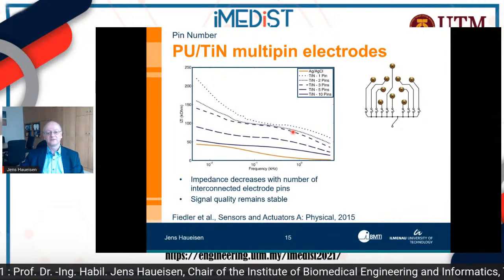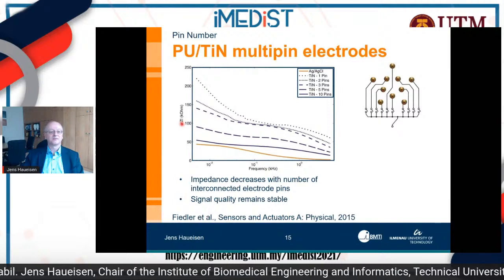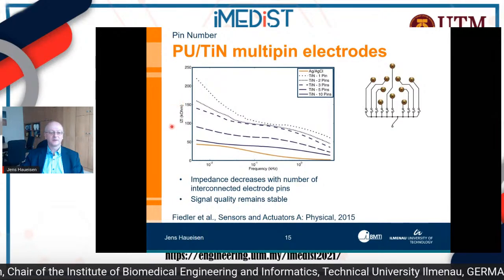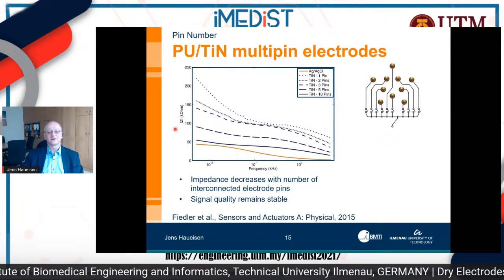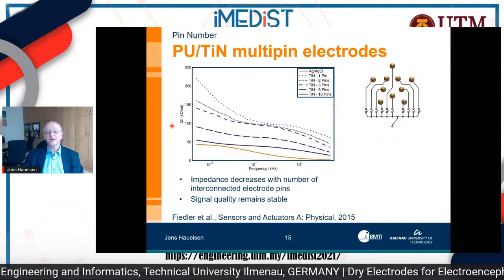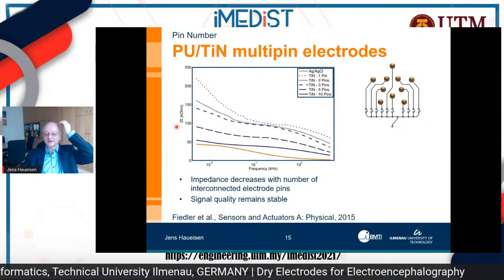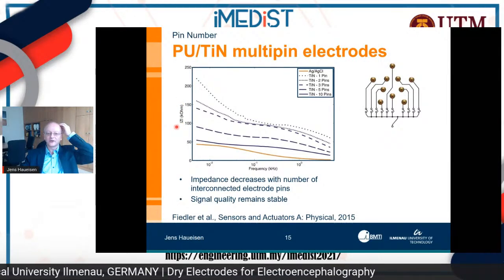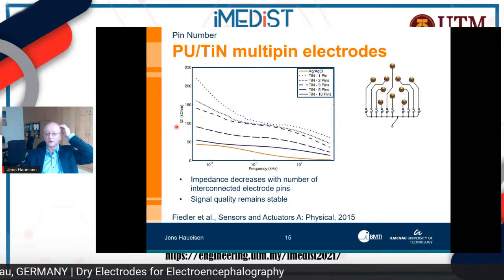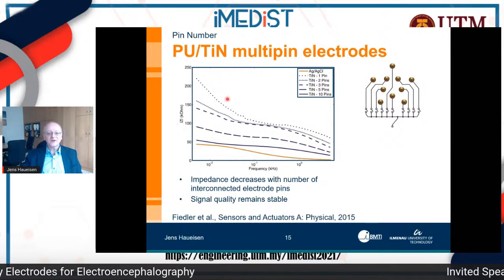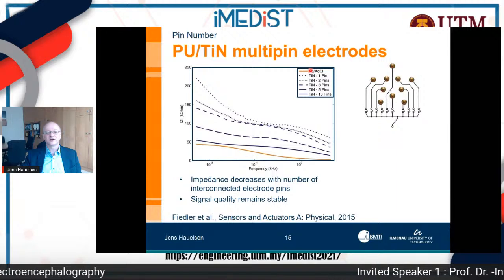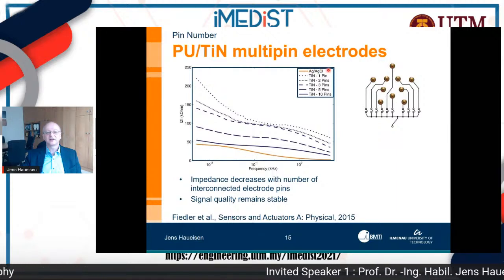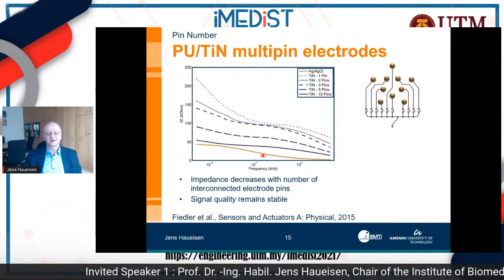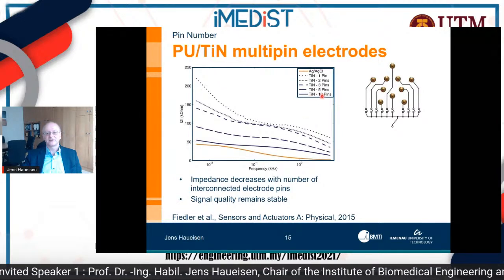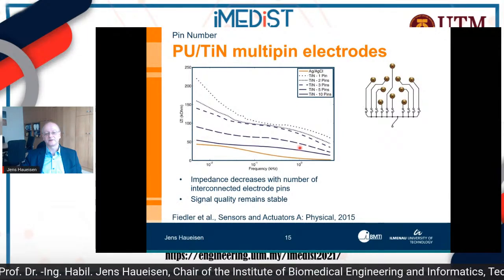And what you get here is this impedance value, but consider those impedance values are now in kilo ohm. And we're talking about the impedance at the skin. So this is measured actually at the volunteer's skin and not in the bath anymore. So what you see here, the silver chloride gold standard electrode is the one down here with the lowest values. That's expected. But if you have about 10 pins, you're getting close to that already.